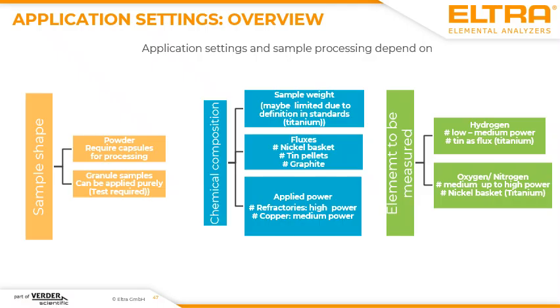One other thing is the applied power. When you are familiar with copper analysis and the applied powers for the analyzer, then you have to think differently when you are now analyzing steels or slags, because then the power has to be much higher to make sure that the analysis works correctly. Again, you have to divide your application into an ON application and a hydrogen application because, on the one hand, the flux could be a little bit different and again, the applied power could be a little bit different.